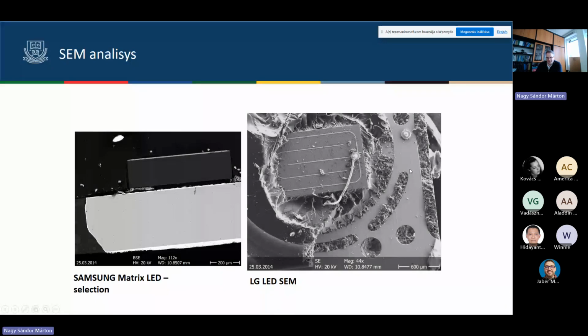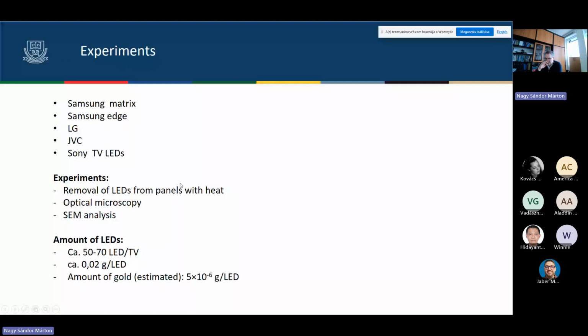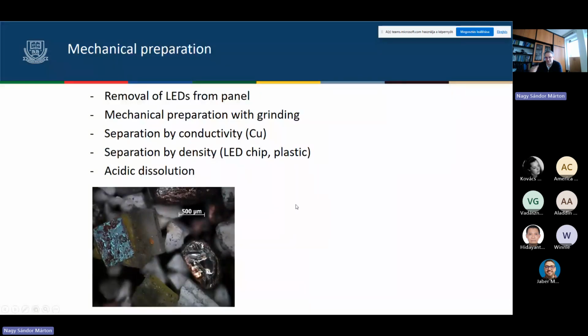During the experiments, we realized that approximately 50 or 70 LEDs are in one TV or one monitor. The mass of one LED is 0.02 gram. The amount of gold in one LED is very low. So the problem is that these are very small amounts, small masses, and so it's very hard to recover them. We are afraid that these valuable materials are actually dispersed in our Earth when they are in LEDs, because the processing is quite hard.